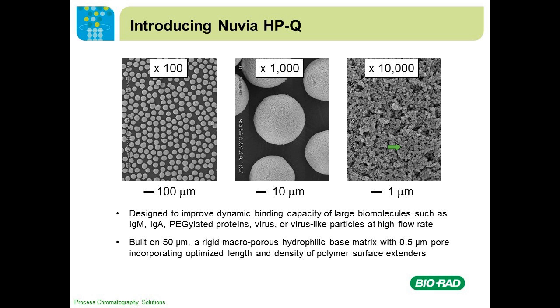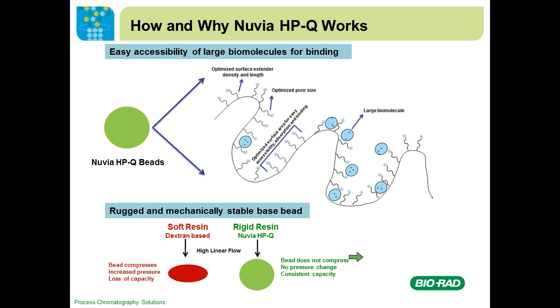But as you can see, with the Nuvia HPQ the porosity is very high, so everywhere the biomolecule is able to penetrate and bind into the resin. And as I mentioned, the Nuvia HPQ base bead has a large pore, which is easy for large biomolecules to penetrate. And we also optimized the graft technology to increase the binding capacity, as you can see on the slide. So the graft technology offers a lot of binding sites. Meanwhile, the pores are still large enough. They do not eliminate the mass transfer or the diffusion for the large biomolecule.